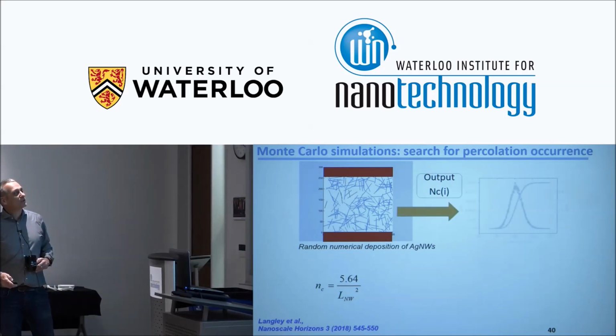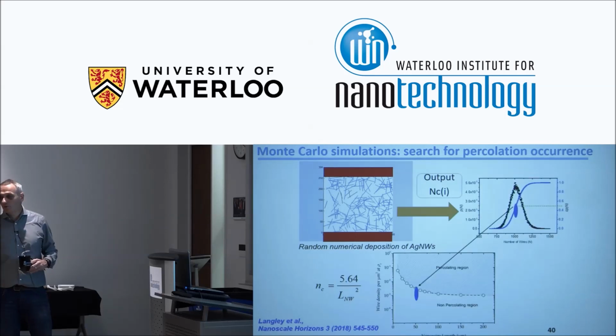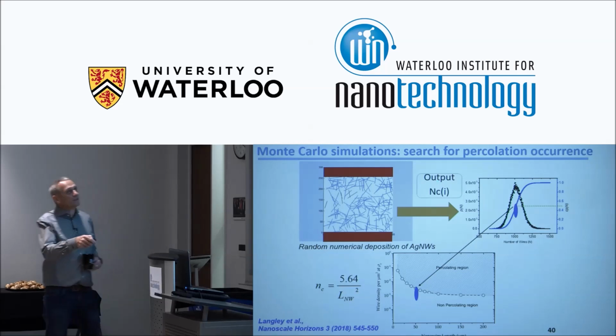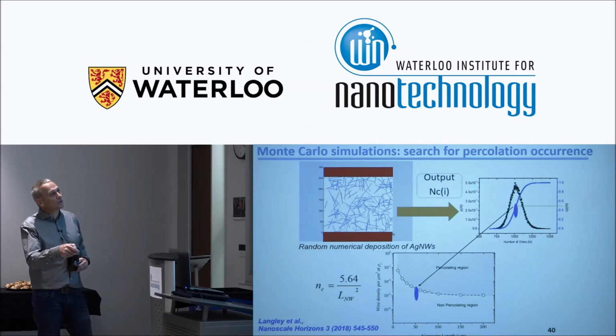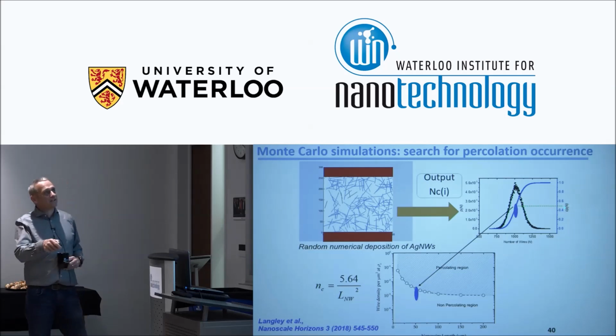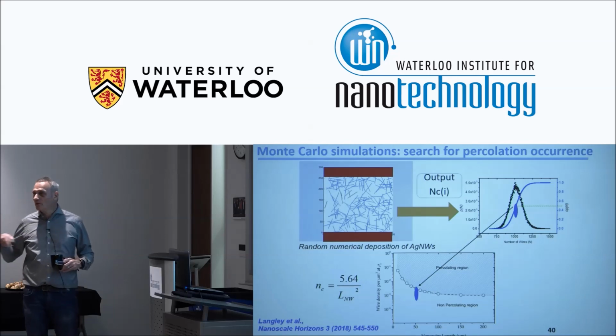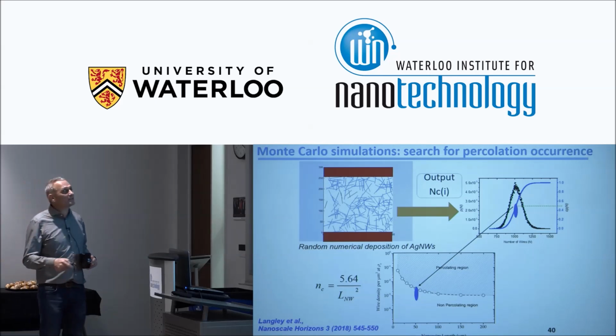So often we multiply that for, let's say, something like 10,000 or 100,000 simulations. And then, for example, we can plot here the probability of percolation occurrence versus number of wires. How many wires we have to put in order to reach percolation. And this is curved like this, okay? That's a kind of Gaussian. And if we plot in violet the cumulative probability, here we didn't put a lot of nanowires, so the probability of having percolation is 0. Here we put enough nanowires that percolation is nearly sure, so we have a probability of 1. And one way to define the critical density is to say, okay, when the probability is 50%, we have the number of nanowires, this is a critical number, and we just divide by the surface of the network, and this is the critical density.